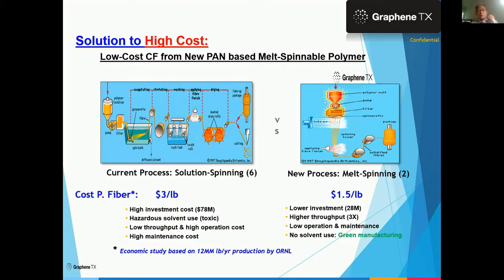As you know, since PAN-based, polyacrylonitrile-based carbon fiber was introduced in the late 60s, every carbon fiber manufacturer is using PAN-based solution spinning to make carbon fiber. It involves a 6-step process, and also it requires a high investment. Based on an Oak Ridge National Lab study, the investment is $78 million, but with melt spinning it would be only $28 million. And also, since you don't go through many steps, and it's high throughput, especially since you are not using solvent, you can melt spin faster compared to spinning in solution. And of course, it also has low operation and maintenance cost. So I like to call this really green manufacturing.